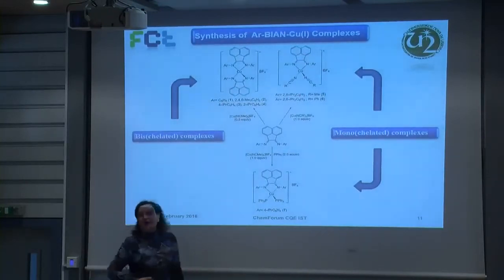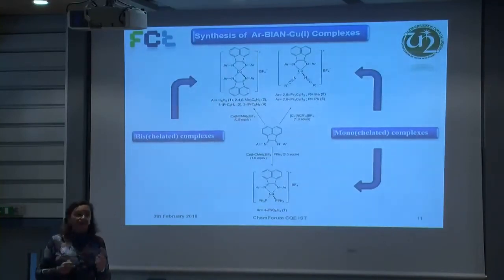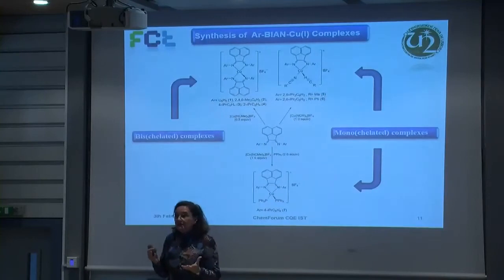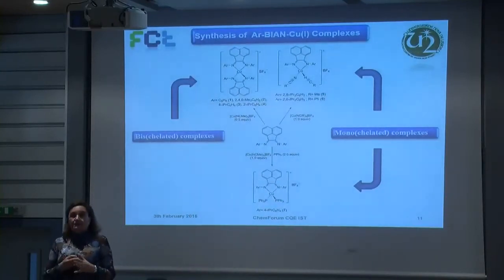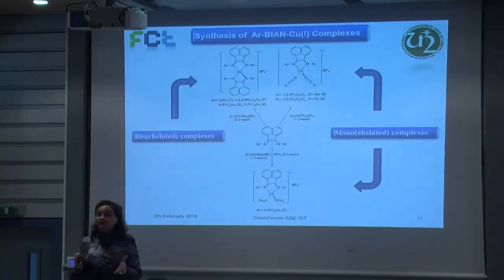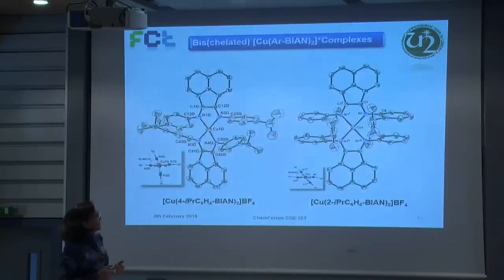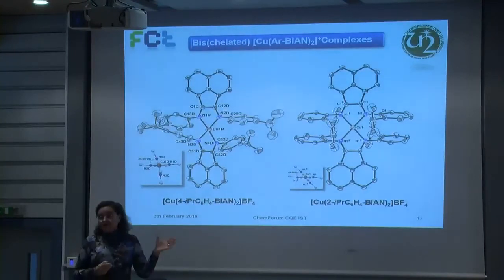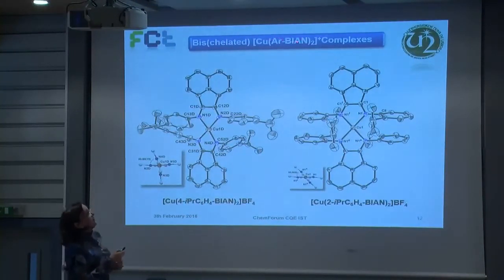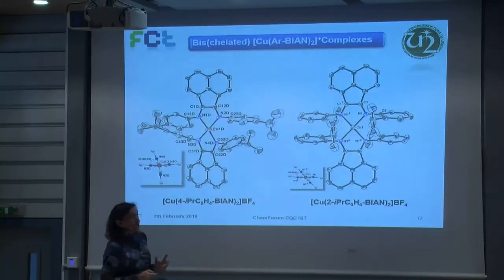If, instead of having nitriles, we wanted to have another ligand, then we put it in the reaction mixture, like in this case the triphenylphosphine, and then we get the triphenylphosphine complex. These syntheses were not difficult, and in most of the cases we could get single crystals for X-ray structure. For instance, there are two examples here of bischelated complexes. In this case, it is the 4-isopropyl in the arene of the BIAN ligand, and here is the 2-isopropyl.